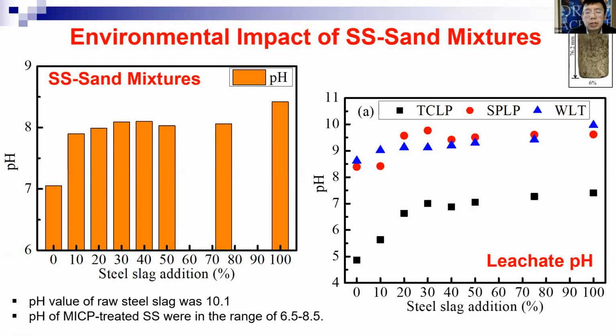So we use MICP to treat this steel slag. Remember, we put in different percentages of the steel slag, and we want to look at the pH of this MICP-treated slag, because MICP-treated steel slag will form a cylinder shape. The cylinder shape is what we run compression testing on first, to see how the strength increases. That's the first thing we got. And once we run unconfined compression testing, we break the sample, so we can measure the pH. Then we can also put a part of this broken sample through the TCLP, SPLP, and water leaching tests. We can also look at their pH and how the pH changed.